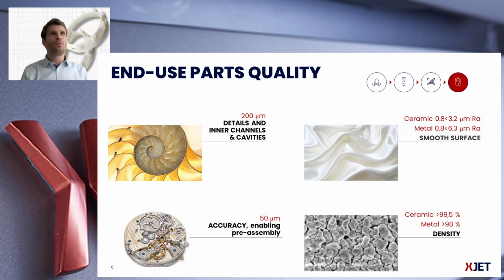And this all results in what we call end-use parts. And why we consider them end-use parts and why we think this is true, I will show you on this slide. So we can print details, as I mentioned, inner channels and so on, down to a level of 200 microns. We can create smooth surfaces with an Ra value of 0.8 to 3.2 microns in ceramics and 0.8 to 6.3 microns on metal. Additionally, we can create highly accurate parts of plus minus 50 micron that enable us to print pre-assembled parts that can even move and are also end-use parts, for example, in the medical surgical environment. And now the last advantage is our density. For ceramic, we can create a density of more than 99.5%, and for metal, more than 98%.